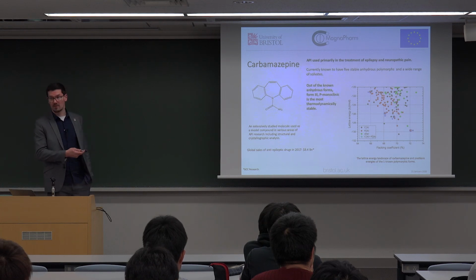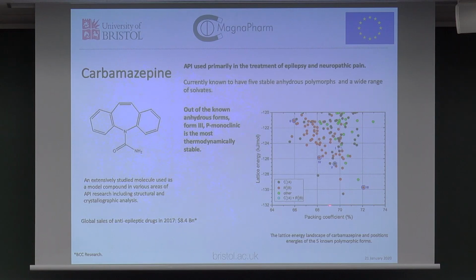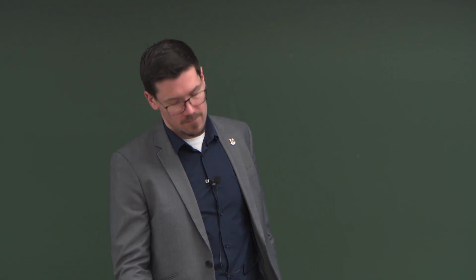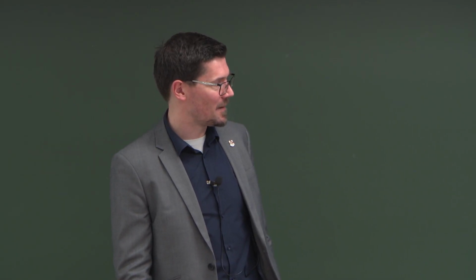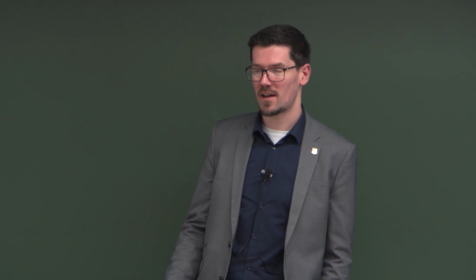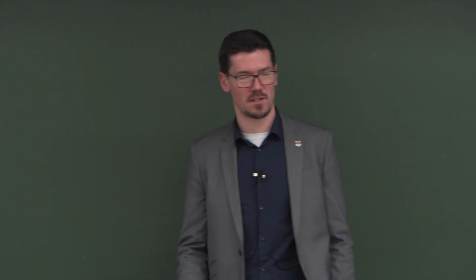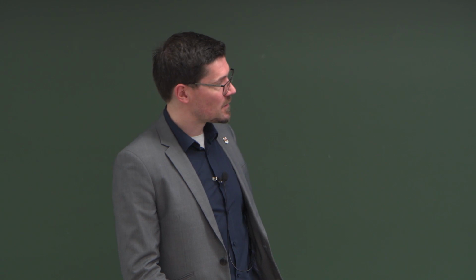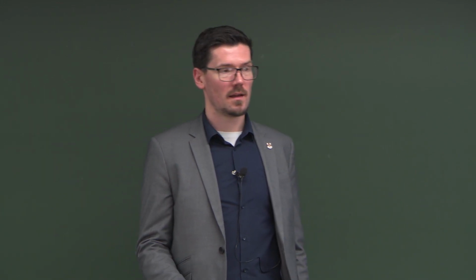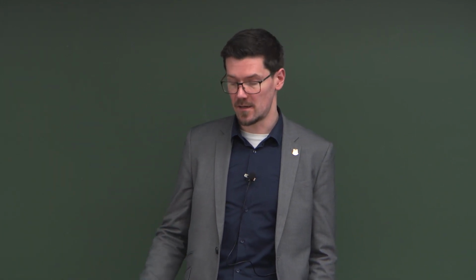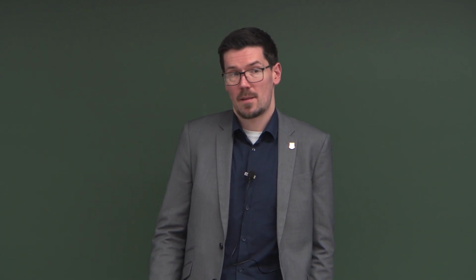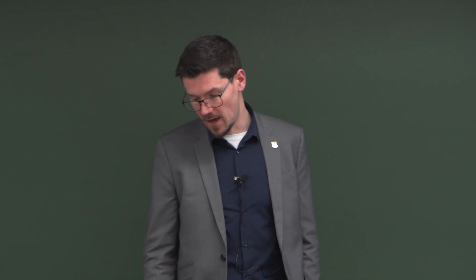So I started looking originally for this little black data point down the bottom, which there's a whole other reason why that's difficult to get, but it seems to be the lowest energy. Why no one's seen it yet, I mean, it makes sense, but I'm not going to go into that here. Anyway, so I did the low temperature powder diffraction on it, again, to see if there was any kind of phase transition from one to the other. And what I see is nothing. There's just expansion, contraction, that's it, no phase transition whatsoever. So am I to expect anything to change with carbamazepine?